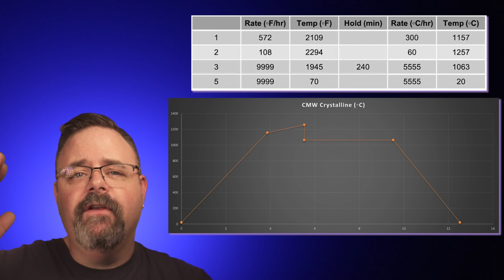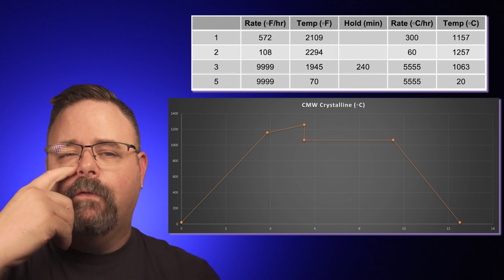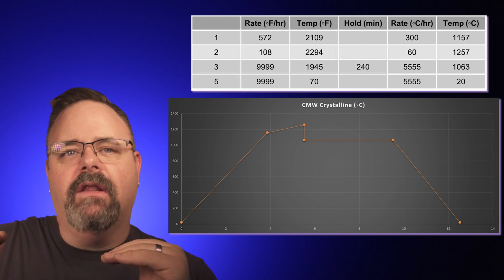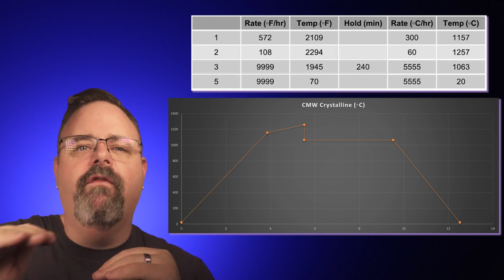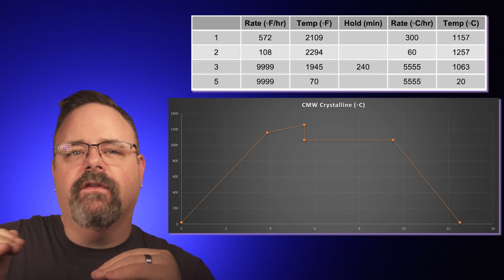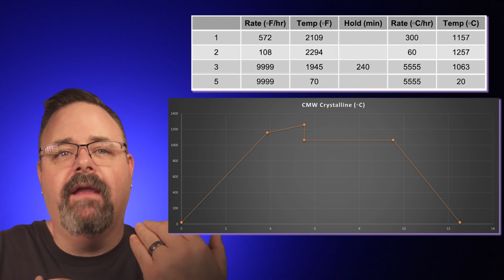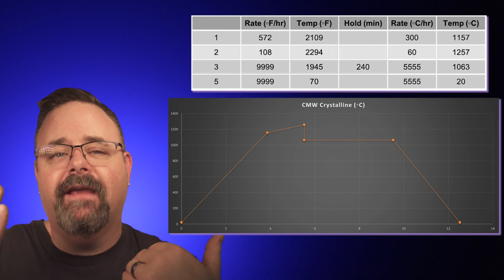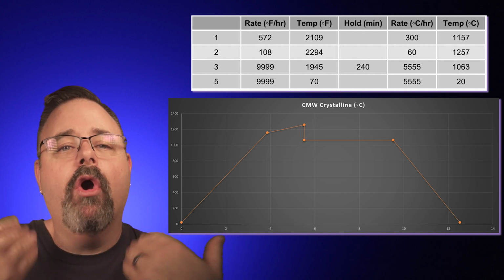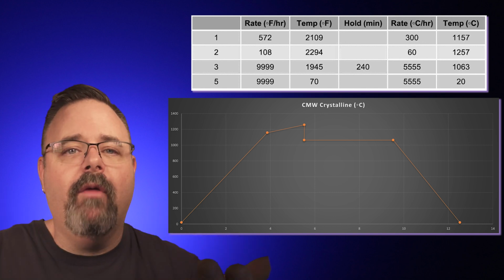The last thing we really need to talk about here is the firing cycle, because that is definitely important. Not just the peak firing, but the steps you take in the firing. You see, traditional zinc silicate crystalline glazes are known for a firing cycle like this, where you go up to your peak temperature, then you allow the kiln to crash cool, and then you sit at a lower temperature, something like cone 04, and that's to allow the crystals to grow. If you took a kiln with a matte glaze and a crystalline glaze and a glossy glaze next to each other, and you open them up at peak temperature, they would all be glossy.